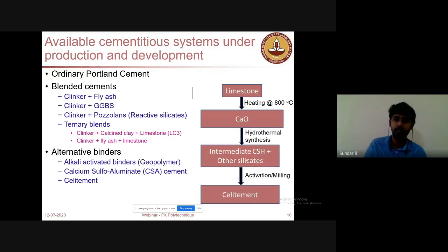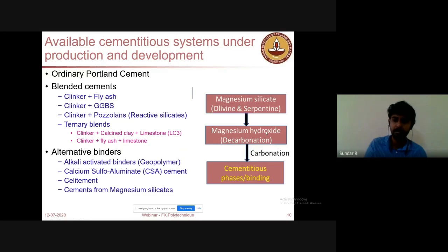And Celitement. This is another cement where the entire process will be different. Instead of clinkerization, they go for autoclaving. That is a hydrothermal process where the cement is manufactured. Similarly, magnesium silicate cements are also there, where the raw material is entirely magnesium silicate. Until now, you have seen cements based on calcium and silica. Here, the cement raw material is magnesium silicate, a green colored rock, something like olivine or serpentine, which are available in the earth's crust, somewhat less than calcium, but still widely available. So that could be one of the alternative cements.